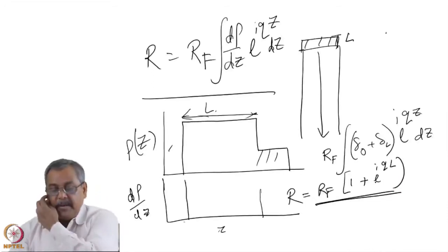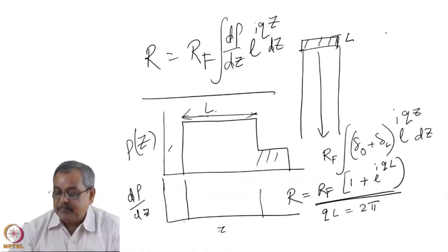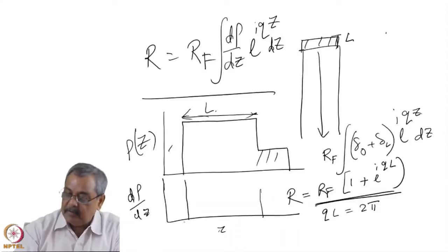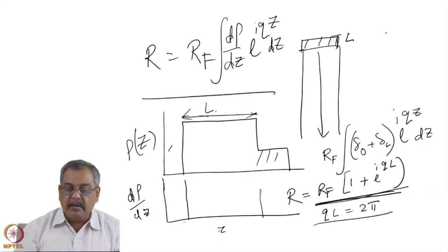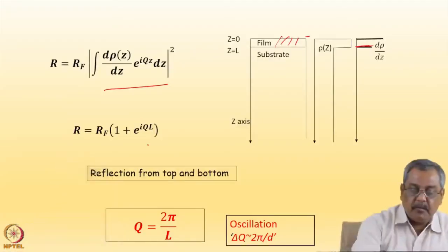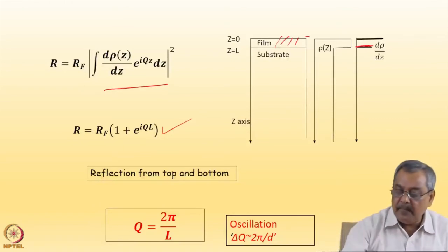Now from here you can see whenever qL is equal to twice pi, then this becomes 2. When it is pi, it becomes 0, and so there are oscillations, and whenever qL is equal to 2 pi, you will have a peak in the reflected intensity. So this is what I want to show you. This R equals RF into 1 plus e to the power IqL, because there are two delta functions, because the reflections are taking place from the top